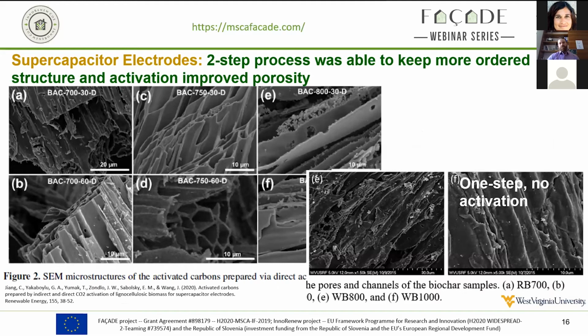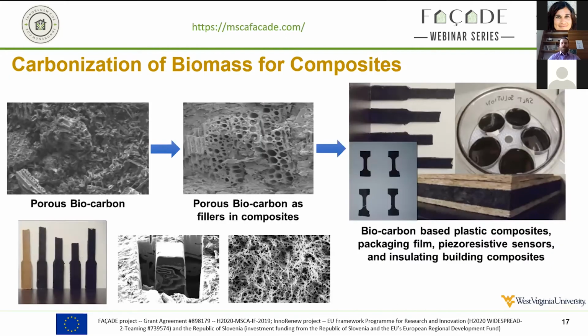So here are some images of the differences. The one on the right side is when you're doing this stepwise carbonization to keep that ordered structure. You can see the channels, the original cell wall of this willow is still pretty well intact, and you can see the pores that are developed in there. The other one is without really any steps, just going straight up to 800 degrees, let's say. This is also the same willow, and you can see this is not a really good ordered structure. Things are kind of broken apart and torn apart, so you don't take advantage of the nice order that you had. Okay, so that's a little bit on these electronic type applications.